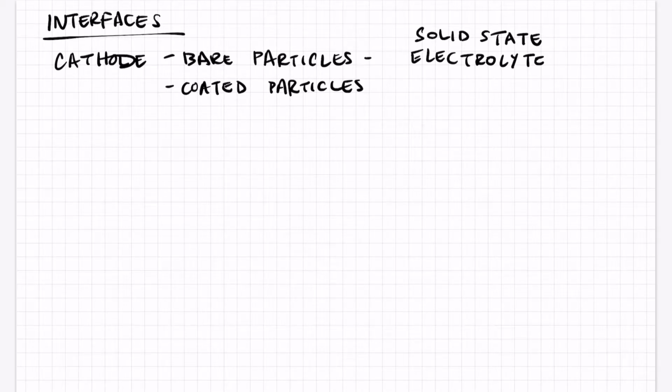The fact that they're dissimilar materials means there's going to be a chemical potential difference, and thus there's going to be an induced decomposition right at these interfaces. And sometimes they evolve quite dynamically, sometimes they don't, depending on the decomposed products.